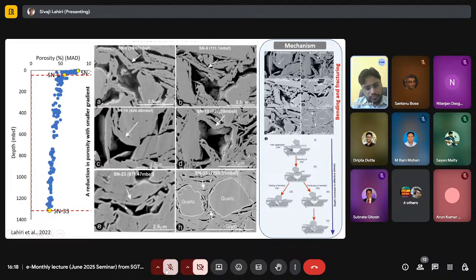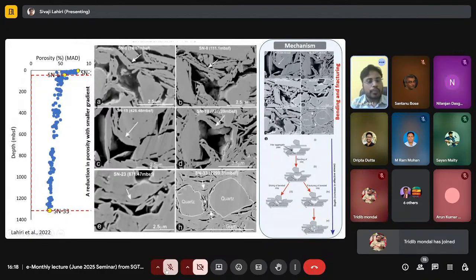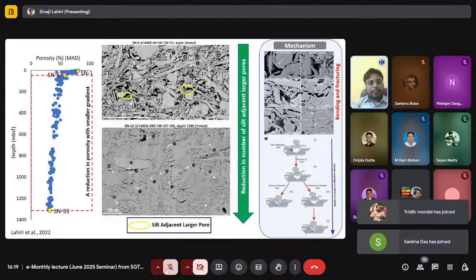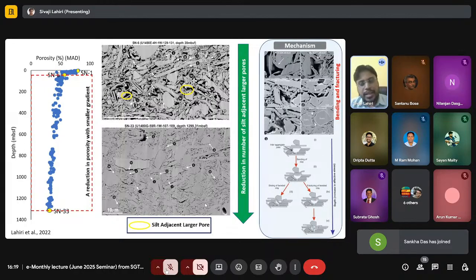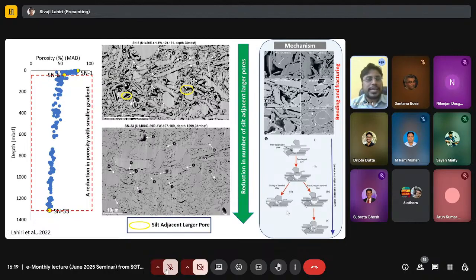You observe here. If one clay particle fractured, ultimately what is happening? 2 small clay particles are getting developed. If 2 clay particles get fractured, then 4 small clay particles will get developed. Now try to look at this particular space, almost 4 small clay particles present. So based on this observation, we can conclude that this particular microstructure is representing a kind of paleo silt adjacent larger pore. The pore space within the 2 silt particles actually got reduced because of the bending and fracturing of the clay particle. So based on this observation, it appears that within the depth range of 30 meter to 1300 meter, bending and fracturing appears to be the dominant deformation mechanism to have reduced porosity in these sample sets.